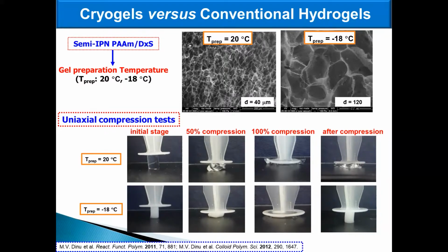On the other hand, the axial compression test has highlighted the remarkable mechanical properties of the materials synthesized by cryogelation. The hydrogels prepared at 20 degrees Celsius fractured under relatively low deformation, suggesting that cracks develop easily in the conventional hydrogel. However, those obtained at minus 18 degrees Celsius were very tough and could be compressed up to about 100% strain without any crack development. This high mechanical strength originates from the particularities of cryogelation, when the reaction takes place in the non-frozen microphase where the monomers are concentrated, unlike the hydrogel prepared at positive temperature, when the polymerization takes place in the whole reaction system.